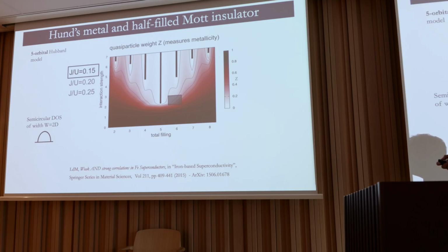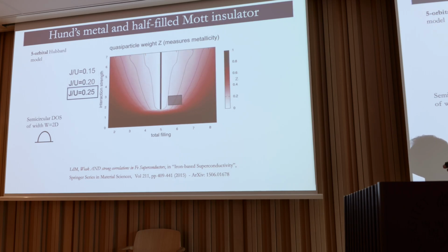So if I increase now the ratio J over U, you see what happens. Really the phase diagram of this model becomes dominated by the distance from this half-filled Mott insulator. And this square here is where you would put in an equivalent 5-orbital Hubbard model, the iron-based superconductors.